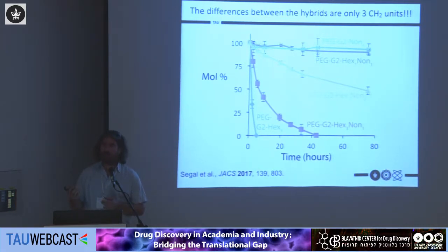The fact that changing a polymer weighing about 6.3 kilodaltons by just three carbons produces such a change in degradation rate is remarkable. I think this should make all of us reconsider the effect of polydispersity when designing amphiphilic block polymers or any molecule that can self-assemble, because aggregation is highly influenced by hydrophobicity and this in turn highly influences enzymatic degradation.